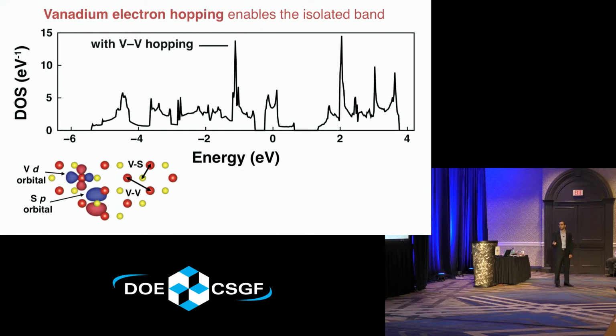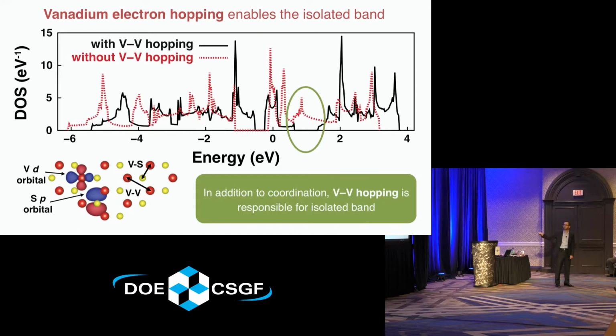However, we find that if I remove that nearest neighbor vanadium-vanadium interaction, so this kind of electron hopping, we would get a qualitatively different spectrum, and we would lose that one band quality. So we would still have the gap below, but we would miss that gap above. So what does this mean? This essentially tells us that it wasn't just that trigonal prismatic coordination that allowed us to achieve this rare property, but also appreciable vanadium-vanadium direct interaction, direct electron hopping, that allows this single-band correlated electronic structure.